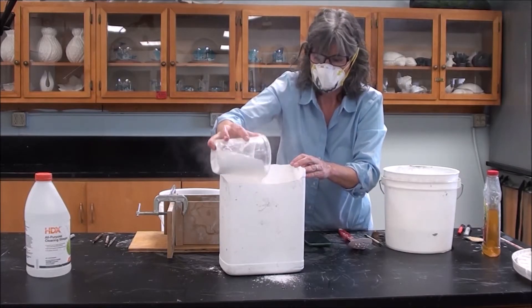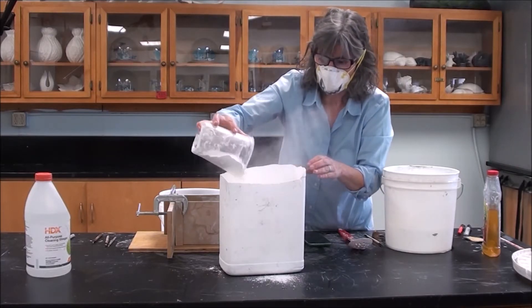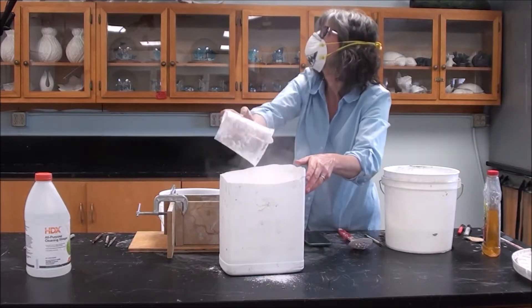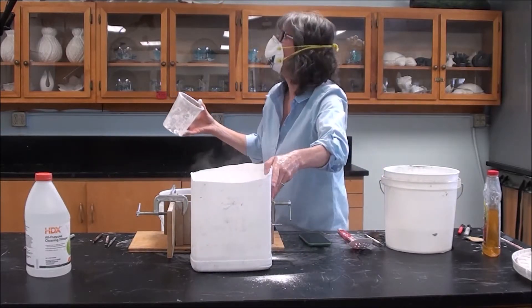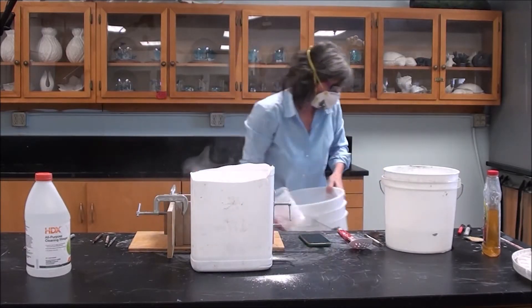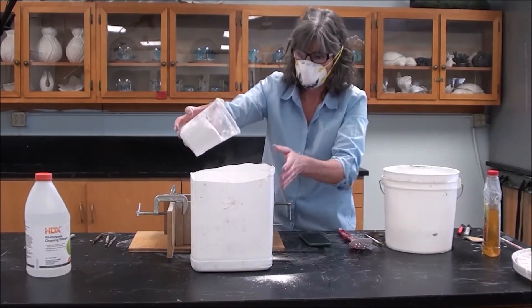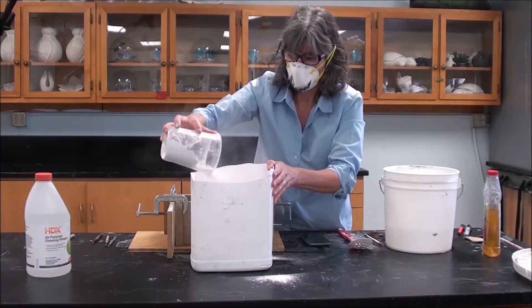When I sift the plaster into the water, I sift it in fairly slowly. I don't just dump it in because if I do that, then I'm going to create large lumps of plaster in there which will take longer to hydrate, and it has the potential to cause lumps in my plaster when I begin to stir.